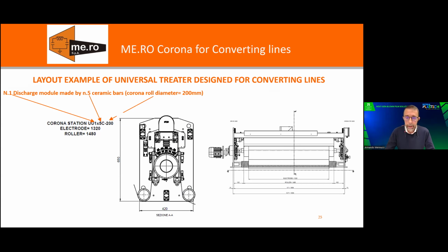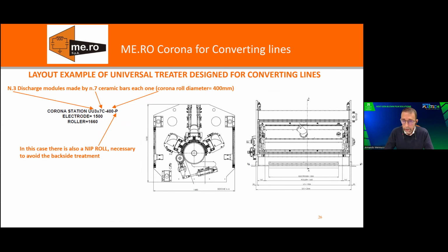Very quickly, we can design a ceramic bar system with whatever number of ceramics you want. It can be 5, 6, 7, 20 ceramic bars. Here is an example with 5 ceramic bars. It's a typical design we do for flexo printing machines, for example, running at 350, 400 meters per minute. Here, instead, we have an example of a much bigger corona station with 21 ceramic bars. This is a classic installation that we use for extrusion coating for aseptic packaging, for liquid packaging. Because the speed can be 600, 700, 800 meters per minute, the power that you need to discharge is high, and consequently the number of ceramic bars must be related to the power that you want to discharge.